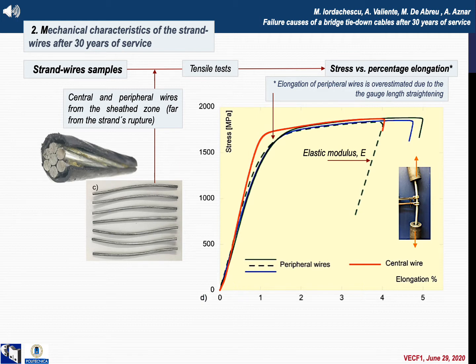1860 megapascals, and offers the certainty of considering it the tensile strength of steel wires, since it is reached by plastic instability when the specimen's curvature has vanished and the stress state in the wire's cross sections is uniform. The elastic modulus of the cold-drawn eutectoid steel from which the pre-stressing strands are made, 205 gigapascals, is compatible with the unloading line slopes recorded during testing.